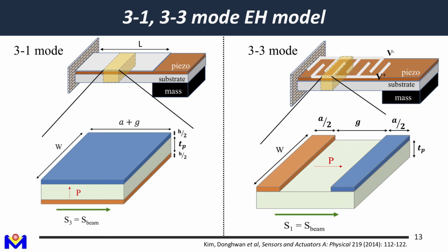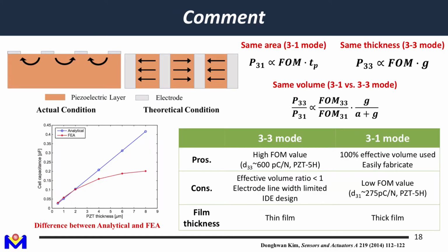And for switching modes, effective volume, we have two different meanings. I will mention this later. And the first important parameter here is to have a very big gap between the interdigitated electrodes. But it will be very difficult to pole the piezoelectric material in the poling process before we can activate the piezoelectric effect. So switching mode is in general not so easy. And the most important reason for the difficulty of switching mode is also here.